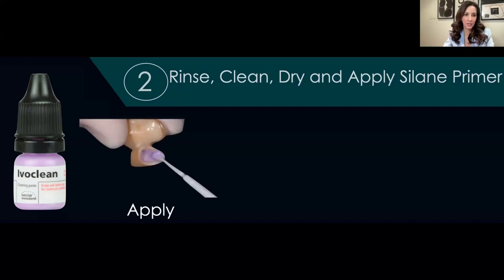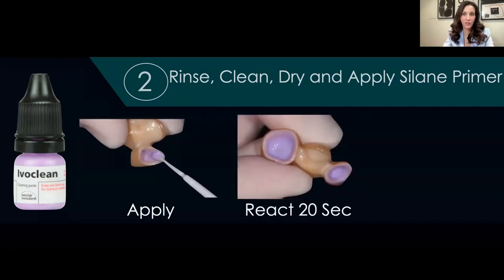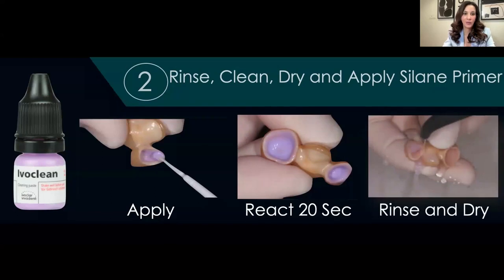And so this slide shows the utilization of Ivoclean, and onto a clean surface, you need to apply a silane primer. Now, the caveat to that is often the silane is actually contained within the bonding resin. If that's the case, so if you're using Scotchbond Universal or Adhese by Ivoclar, you don't necessarily need a separate silanating step. So suffice it to say, you have a clean veneer surface, apply silane to it.